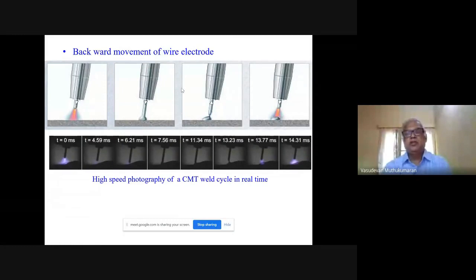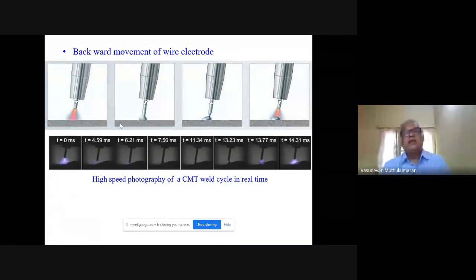Then the wire is made to withdraw. The weld droplet detaches from the filler wire and falls onto the material or workpiece to be joined. Then the arc is reinitiated. There is a hot and cold period alternating. It happens very fast. The productivity is not lost, and we get a low heat input, so we can avoid spatter. This is what we are trying out for hard facing and cladding applications.